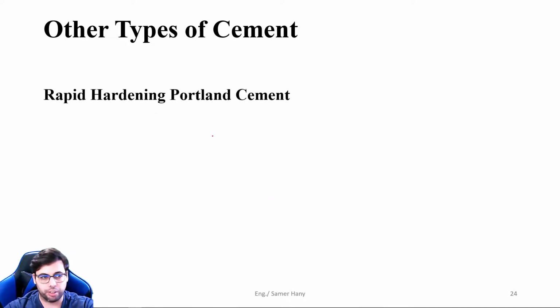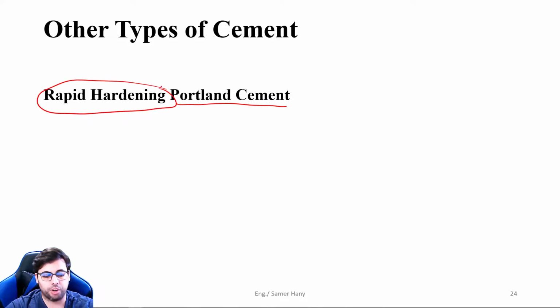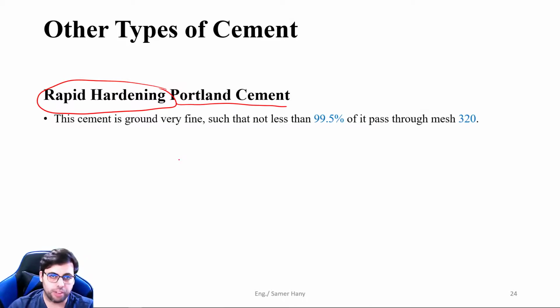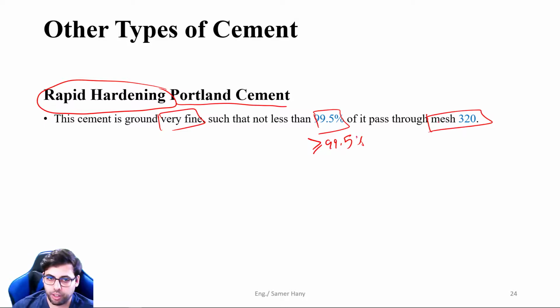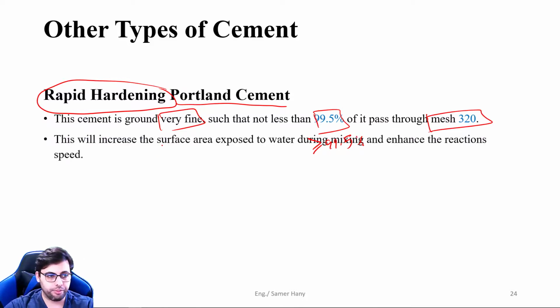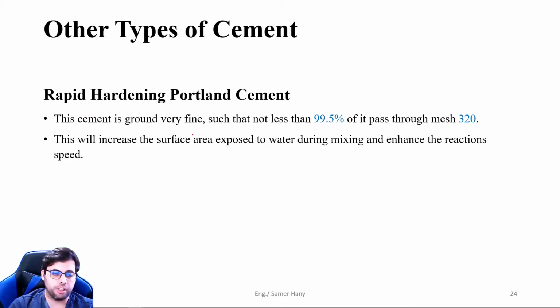So the first type is the rapid hardening Portland cement, and as the name implies, this is just Portland cement, but it's not ordinary Portland cement, it's rapid hardening Portland cement. What do we do extra to this Portland cement to make it rapid hardening? We just physically treat it to grind it more, so that it's very fine, such that higher than 99.5% of the mass passes through a 320 mesh screen. So this is much finer than the standard for the ordinary Portland cement. So it's 99.5 instead of 98, passing through mesh 320 instead of mesh 200. Okay, this will increase the surface area exposed to water during the mixing and the solidification process, and will make the reaction go faster. Okay.